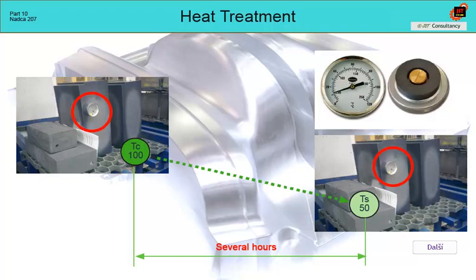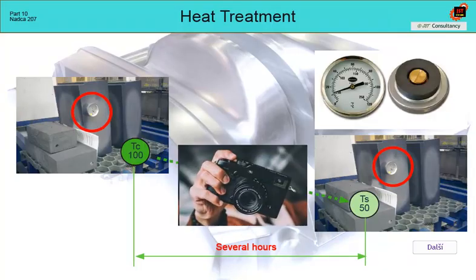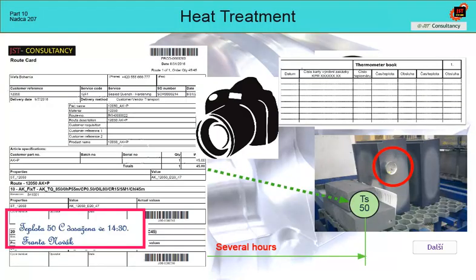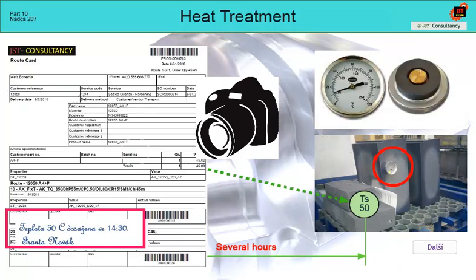In order to avoid future discussions about proving this delay between hardening and tempering cycles, this transition period must be defined and documented. But since the quenched parts are already out of the furnace, this stage of the process is not part of the quenching cycle record. Therefore, this situation must be documented in another form, by a photograph and a manual record on the production order with routing, or with entry to the thermometer book, testifying that the operator measured the surface temperature of the piece on the cooling station with a magnetically clamped thermometer, or in another way, and that the temperature reached, before placing it in the tempering furnace, was really Ts equals 50 Celsius.